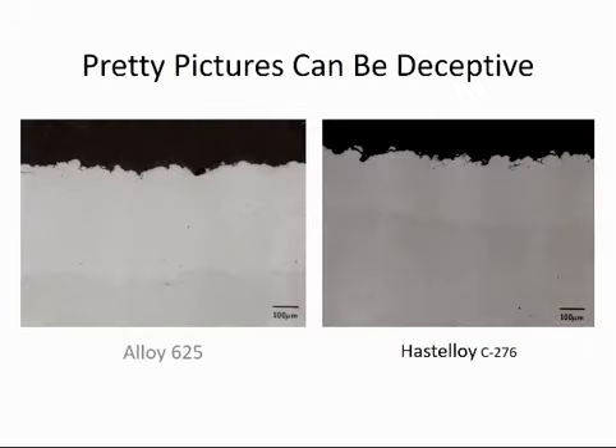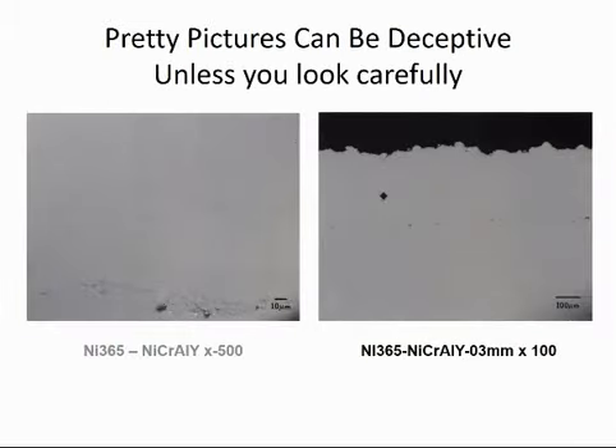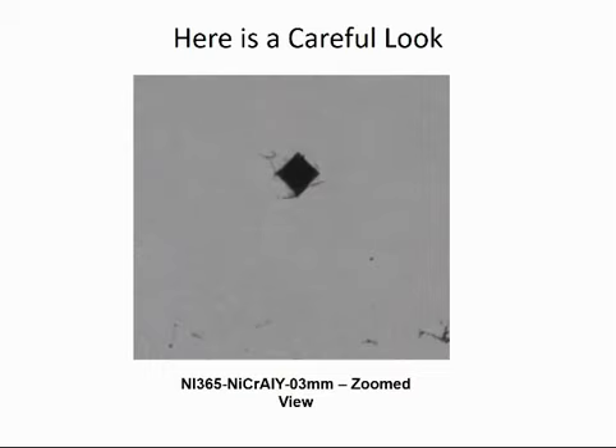Here we have an example of some very nice looking metallography that you would think would be absolutely wonderful in every regard. These happen to come out of an HVOF evaluation, and they both look great. Alloy 625, alloy C, perfect looking coatings until you start to look closer. Now, if you just magnify things, you don't see anything that looks ugly. But wait, what's that there? It looks like an indenter, doesn't it? Maybe we get a little, oh my, there we have it, cracks. This was a K1C evaluation. This otherwise gray looking coating was brittle.